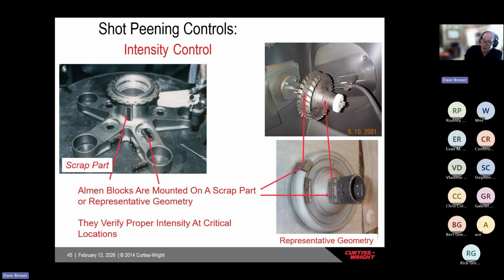The same almen strips are run at the end of the lot, so you can verify that the settings of the machine haven't changed. If anything changed, you'll be able to identify that with an incorrect almen strip reading. A scrap part is great, but in some cases, like this turbine wheel, it's difficult to get a scrap one, so you're allowed to manufacture a representative geometry. Wherever you see these blocks, that's where they're interested in measuring the shot peening intensity.